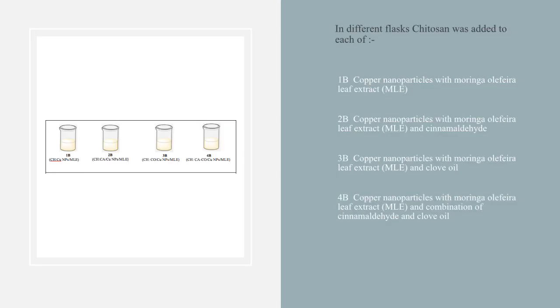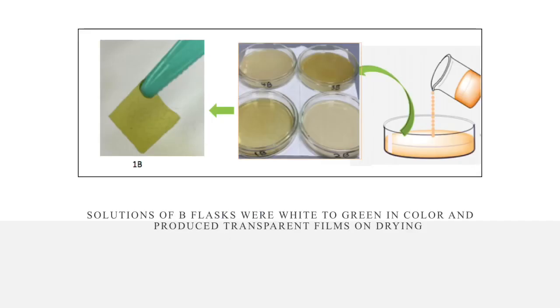And here, as you can see in the figure, in different flasks, chitosan was added to each of the following: 1B copper nanoparticles with moringa leaf extract, 2B copper nanoparticles with moringa leaf extract and cinnamaldehyde, 3B copper nanoparticles with moringa leaf extract and clove oil, and 4B copper nanoparticles with moringa leaf extract and a combination of cinnamaldehyde and clove oil. Then the solutions of B flasks were as well poured into petri dishes to dry at room temperature. They were white to green in color and produced transparent films on drying.